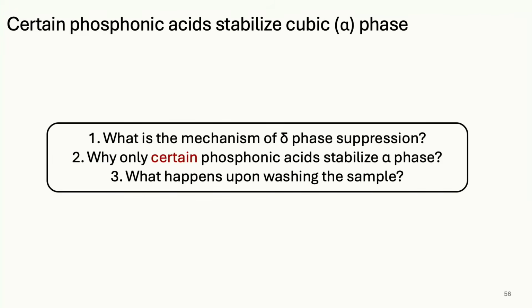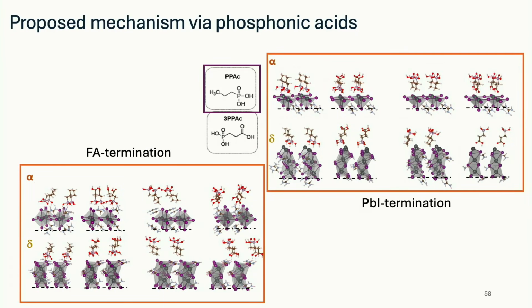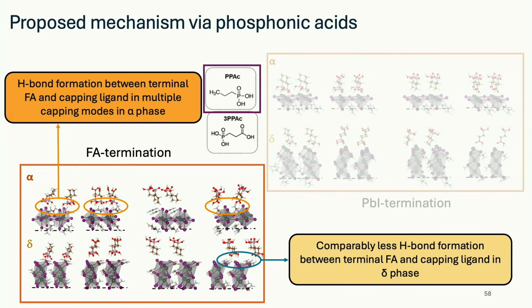And we were able to answer all this, and it comes down to the idea that the crystal would like to bind to these phosphonates. You see, the crystal as it grows has all these dangling bond sites, so the phosphonates would bond to it, and it stabilizes them. But actually, the delta phase has a lot of internal bonding. It doesn't really care about the molecules that much. So the point is the delta phase is equally happy either way, but the molecules really favor the alpha phase.